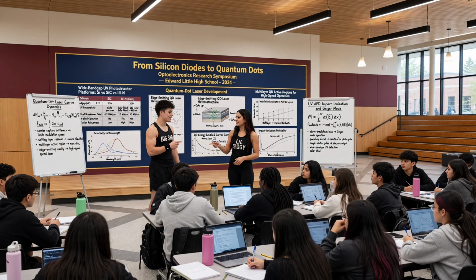So what happens when you shine high-energy ultraviolet light on it? UV photons have much shorter wavelengths, which means they carry drastically more energy than infrared photons. Because silicon is optimized to absorb lower energy light deeply within the crystal, these extremely energetic UV photons get absorbed instantly right at the very surface of the silicon. Often in the dead layer before they even reach the depletion region where the electric field is. Exactly, they burn themselves out before they reach the trap.